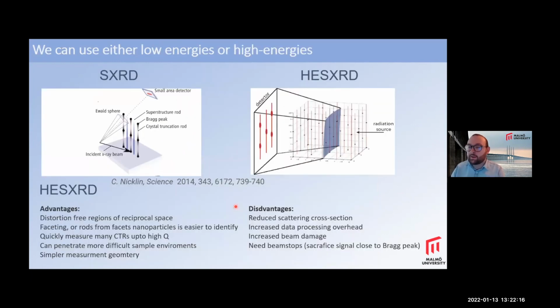And we can use either low energies or high energies. At high energies, you have the advantage that you get this sort of distortion-free image of reciprocal space, and any faceting or rods from nanoparticles are quite easy to identify, and you can quickly measure many CTRs up to a high Q range. You can also penetrate difficult sample environments, and the geometry is simpler because all you have to do once you're aligned is rotate your sample. At the lower energies, you have to move your detector around as well to meet the diffraction condition.